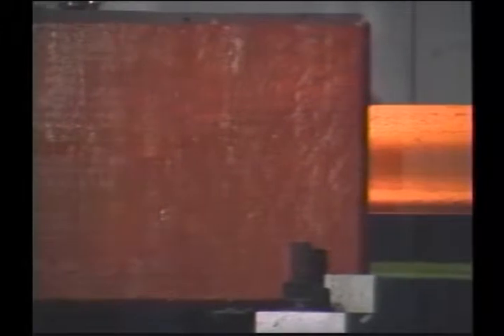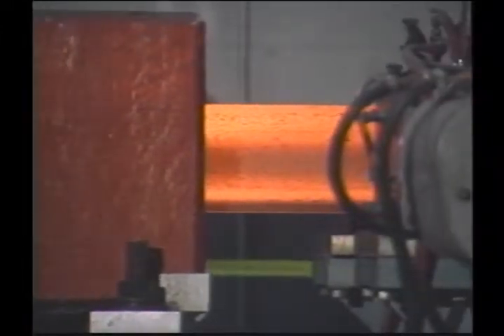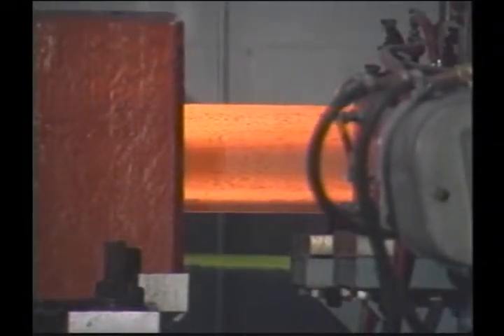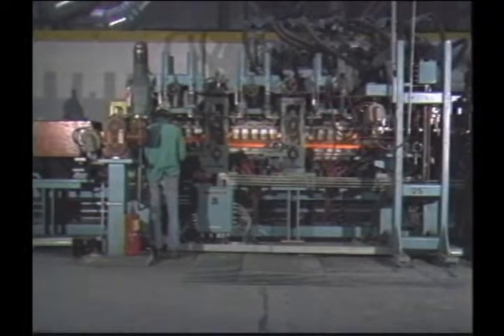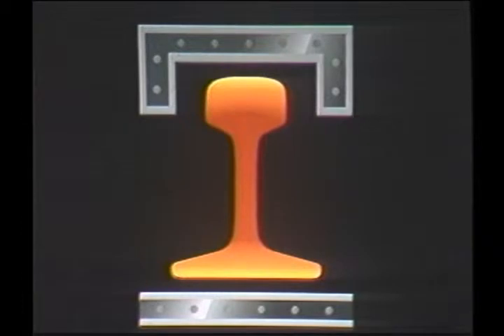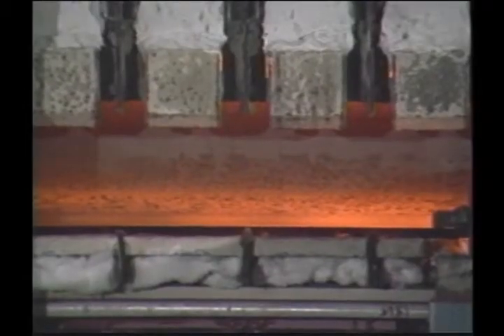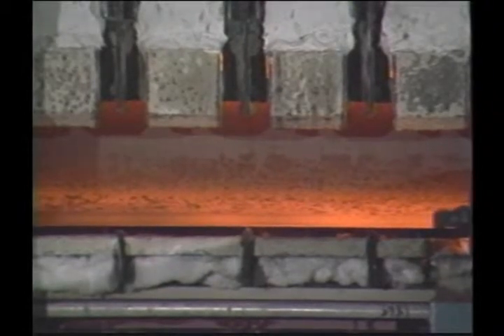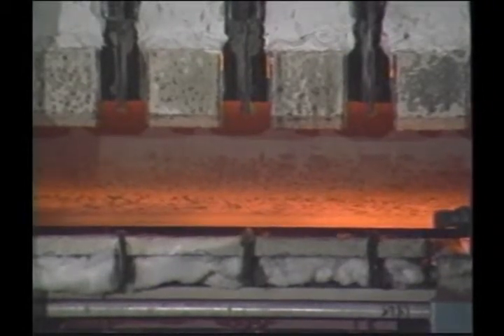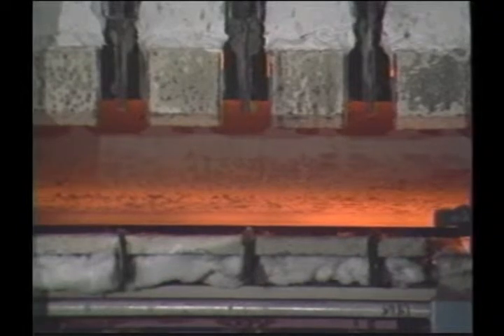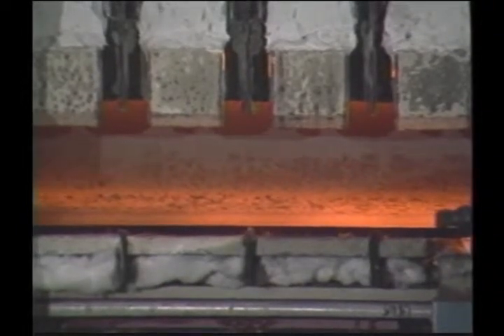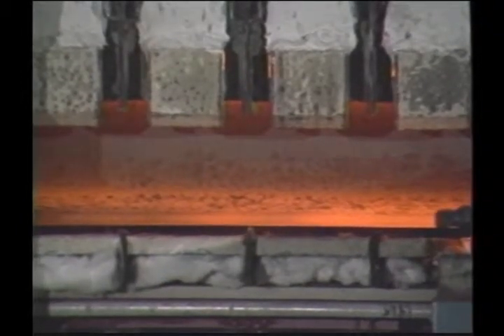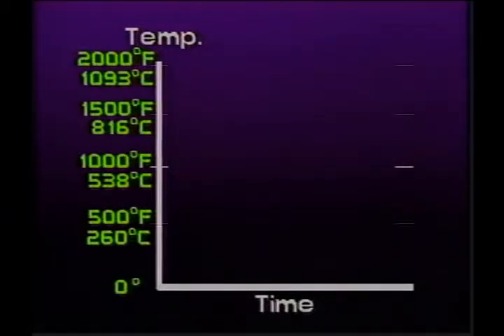The Permatrack process starts with the induction preheat coil, which rapidly heats the entire rail section to about 1000 degrees Fahrenheit or 538 degrees Celsius. As the rail enters the main heat section, top and bottom induction coils produce counterbalanced heating, which keeps the rail straight. Specially designed head-hardening coils raise rail temperature to the critical point necessary for achieving the fine pearlite grain structure characteristic of rails treated by the Permatrack process.